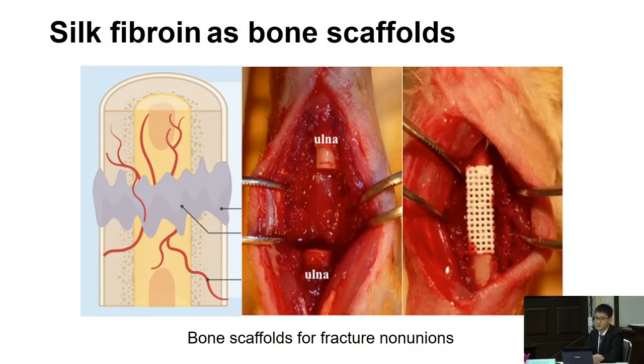So, silk fibroin can be made into bone scaffolds. And what actually are bone scaffolds? When we have a broken bone, an injury in the bone, and this bone is broken, the ulna, for example, you can see that there is a large gap between these two pieces of the bone. And the problem is that this bone won't heal, or it can heal, but very slowly. The problem is because the cells in this piece of the bone cannot communicate well with this piece of the bone.